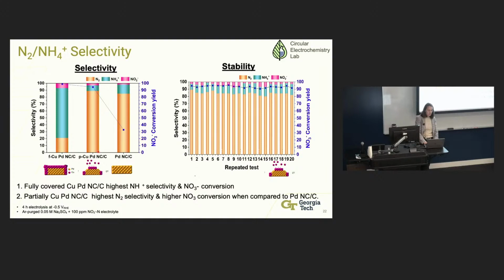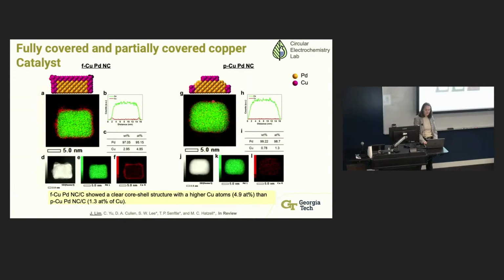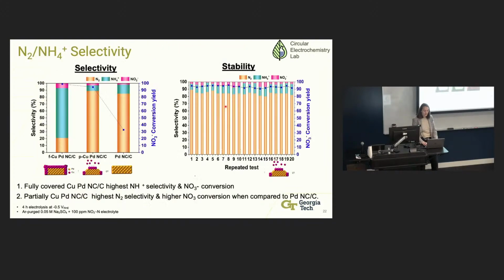And the interesting thing that we saw was that with the fully covered copper catalyst you basically made all ammonia. So this blue is ammonia, the orange is nitrogen, and the pink is nitrite. When you had a core of palladium but then a complete surface coverage of copper, you only made ammonia. Whereas if you had a partially covered copper, just a little bit exposed, if we go back to here, it's still covered in copper, but maybe a less thick layer, we're getting nearly all nitrogen. And so I think this really showed how different your catalyst selectivity can be depending on what surface you have.